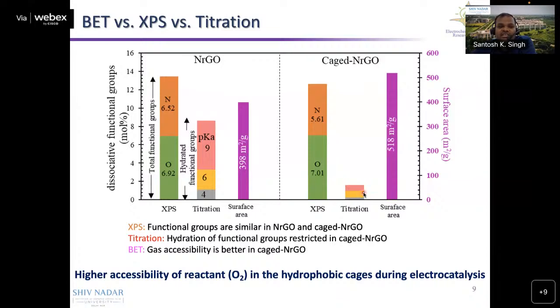It means that the accessibility of water is very low in the hydrophobic cage. However, accessibility is very high in the hydrophilic catalyst. So this is how we believe that if the catalyst is highly hydrophobic, then the oxygen accessibility will be higher. And that is what is responsible for the first step of the oxygen reduction reaction, that is the adsorption of oxygen